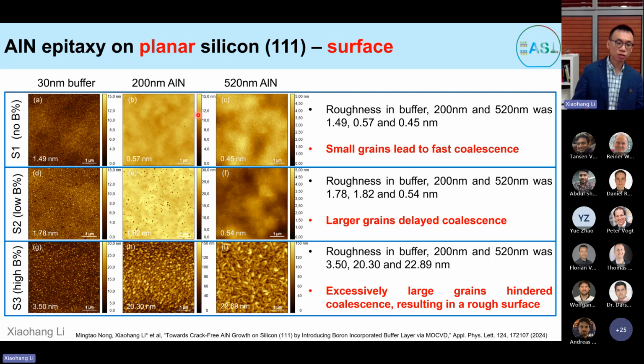After you grow 200 nanometers of aluminum nitride, you can see that the first sample is very smooth. The coalescence has completed. For the second sample, the coalescence is almost finished, but you end up with those pits, which are threading dislocations. For the third sample, you can see that the surface is very grainy, very rough. This is a very typical morphology when you have a lot of boron.